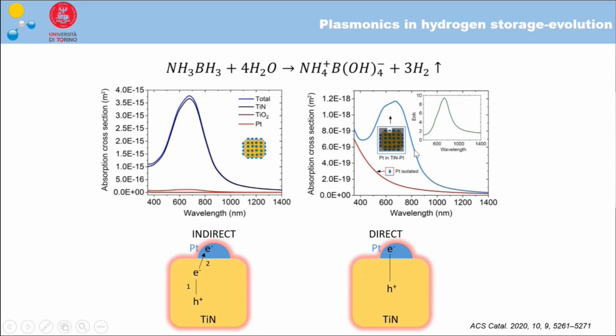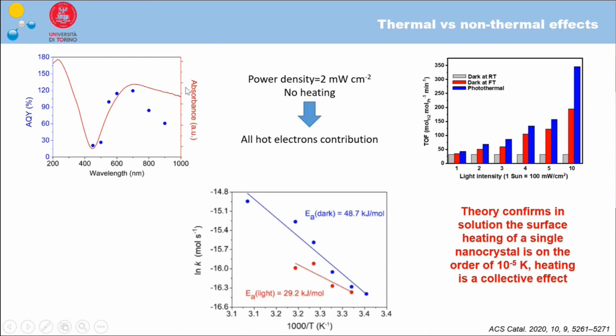This also brings interesting effects, meaning that we can have different mechanisms of hot carrier production. So we can have, for instance, the formation of electron holes in titanium nitride, which then can be transferred to platinum where the reaction occurs, or you can also generate hot electrons directly in the platinum. So this can also bring some increase in efficiency. Here you can see some features of our reactions. The first thing that I would like to highlight is the apparent quantum yield plot on the left-hand side of this slide.